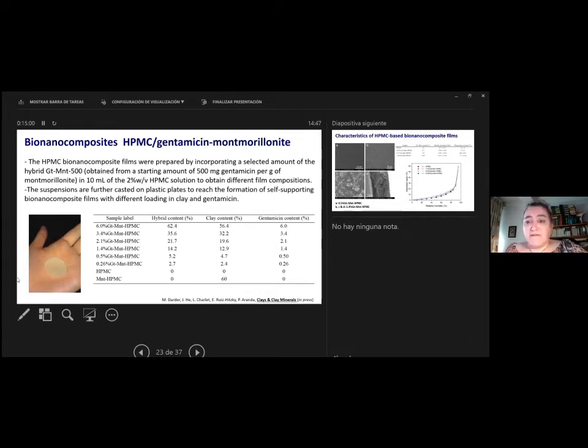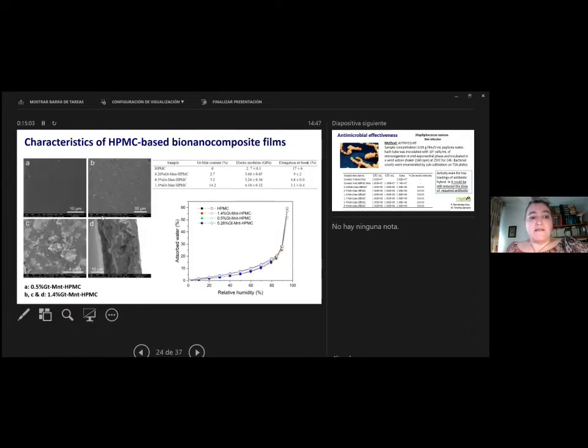This is the aspect under the microscope, a kind of electron microscopy. This biopolymer has, more or less, 15% of intercalation compound, so it's a larger amount than this one, which has a very small amount. This one is more homogeneous, but here we are able to see the clay. But the film is very consistent. The film has good mechanical properties improved by the presence of the clay.